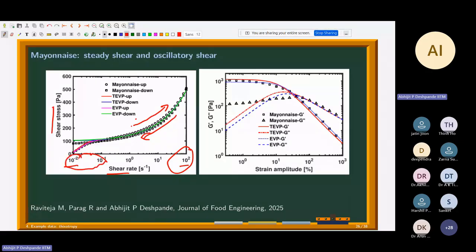So we have basically a built-up structure to a broken down structure as we go from low shear rates to high shear rates. And in terms of this material, we can see that there is a small thixotropic loop. It is not as magnified as some other materials that we have seen, but that's partly because the structure build-up processes are quite fast here.